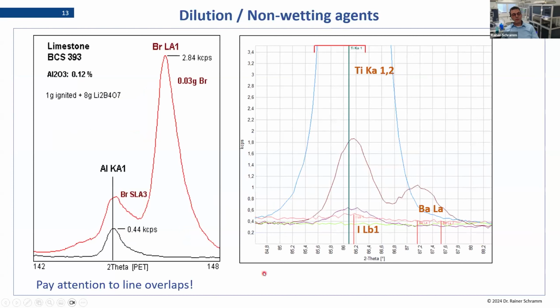But be careful with these additives because they will make line overlaps. The bromide overlaps with the aluminum K-alpha line. It depends on how much bromine you put in, but it goes pretty quick, so that you need a line overlap correction. You really have to be careful there. The same for the iodide with the titanium K-alpha. Here we are lucky because iodide is much more volatile than bromide, so most of this will disappear. But if you have too much in it, then definitely you also have a line overlap, and you need to do some corrections if you want to get reliable titanium results.